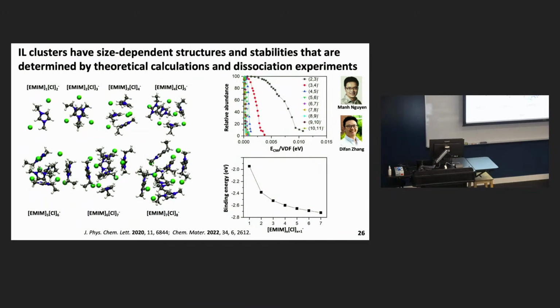Because these species are well-defined and contain well-defined numbers of cations and anions, we can again rely on theory to predict their structures. These are density functional theory calculations on the left-hand side. As I said, we can go through with the mass spectrometer and measure their relative stability as a function of size. So these numbers in the brackets here are just the numbers of EMIM and Cl groups in each cluster. And you can see that the amount of energy required to fragment these drops off precipitously with increasing size. So the bigger they are, the less stable they are towards fragmentation. And this is actually borne out as well in the calculations where they calculated the energy required to remove a neutral unit from each of these clusters, and we see the same sort of decay, which supports the experimental results.